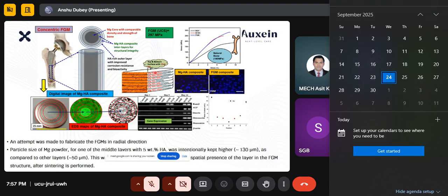If I show you the cross-sectional view, you see there is 0% in the middle, and the hydroxyapatite increases towards the outer layer. So magnesium is the core with a density comparable to bone, and hydroxyapatite with the interlayers provides structural integrity. And we found that the ultimate compressive strength was approximately 297 for this functional gradient material. The blue line denotes the functional gradient material, and you can see it was approximately 297, which was better than 15% HA and better than the pure magnesium.